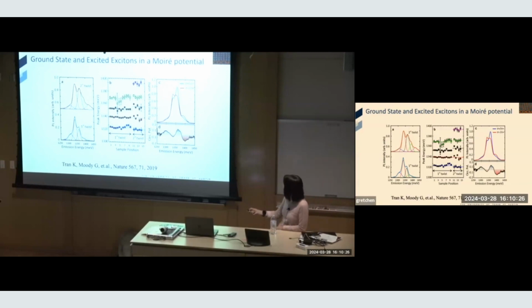So here is a spectrum taken for an interlayer exciton with a 1 degree twist angle. Here is another heterostructure, a two-layer structure made with a 2 degree twist angle. Now I take these spectra at many different locations on the sample. Sure enough, there are some inhomogeneities. The energy fluctuates a little bit, but the energy spacing seems to be getting larger with a 2 degree twist angle. Again, for simple quantum mechanics 101, larger twist angle, smaller quantum pancake, bigger energy spacing. So that's the first indication. Maybe I have something that's related to this quantum pancake.